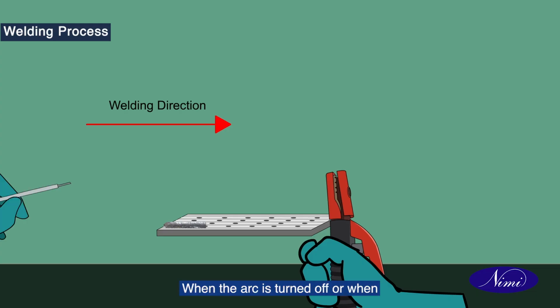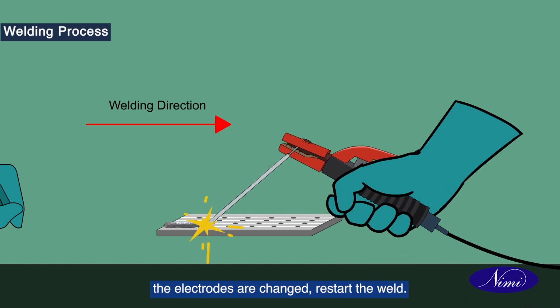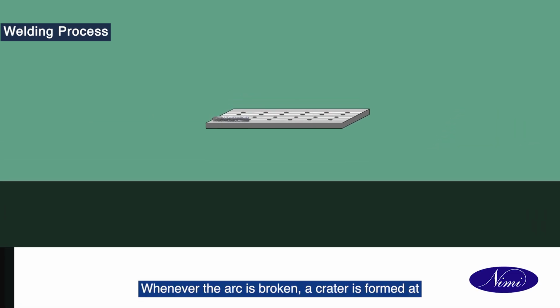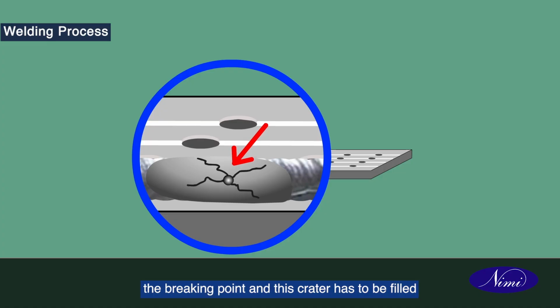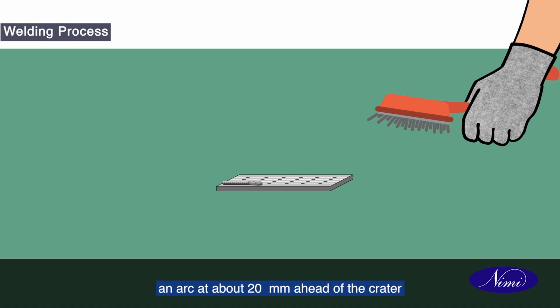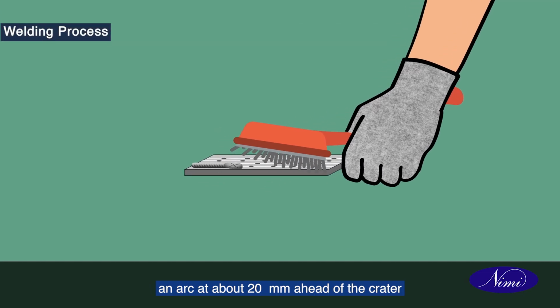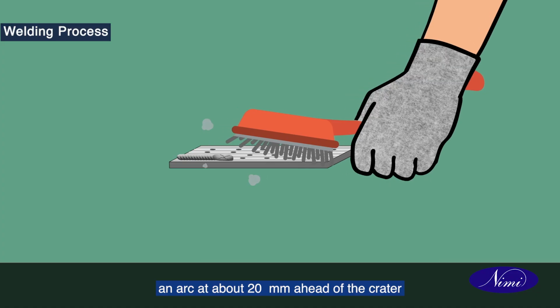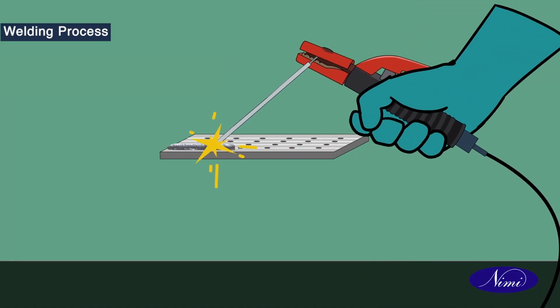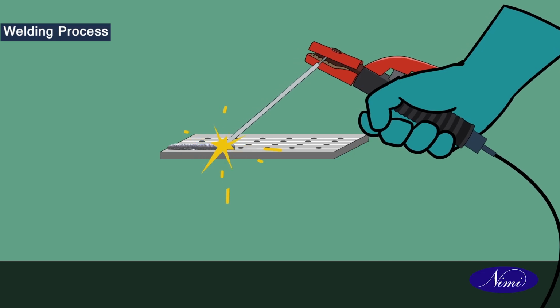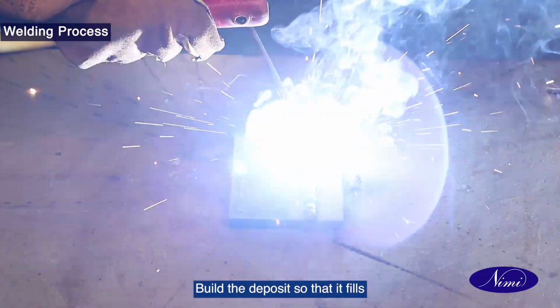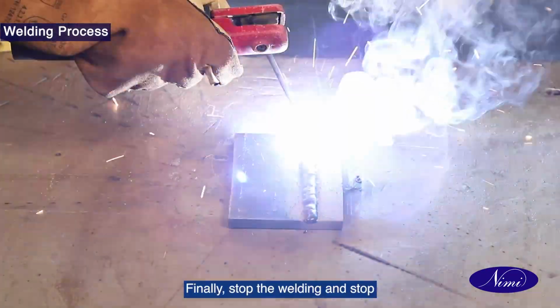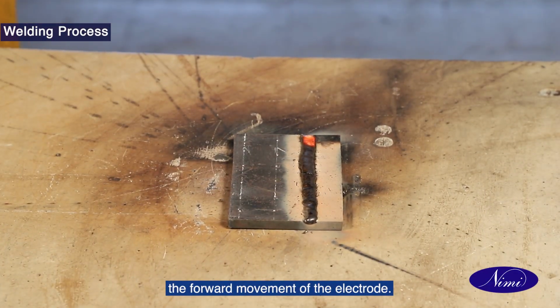When the arc is turned off or when the electrodes are changed, restart the weld. Whenever the arc is broken, a crater is formed at the breaking point, and this crater has to be filled first while restarting the arc. Clean the crater and generate an arc at about 20 mm ahead of the crater, and return to the crater at a faster rate. Build the deposit so that it fills the crater, then move the electrode ahead. Finally, stop the welding and stop the forward movement of the electrode.